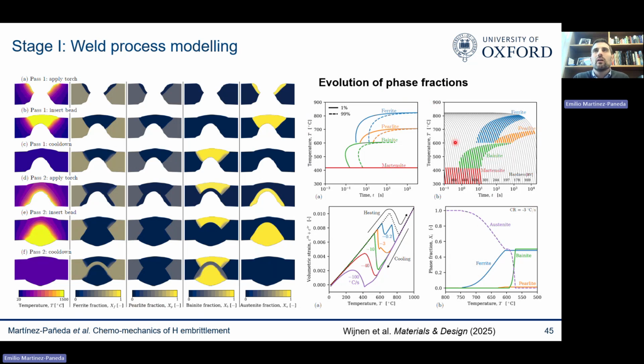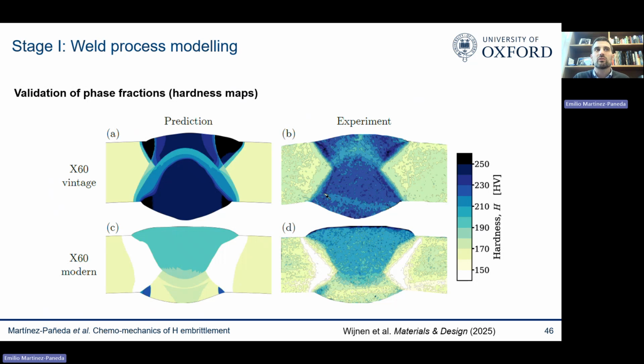These models are relatively empirical, but they're actually quite good, I was quite impressed by them. You can see that, depending on your phase fraction, what is the hardness of your material, so that allows you to validate. You see here two types of welds, we apply the same welding protocol, and as you can see, we got actually quite a good agreement when it comes to the hardness maps, experiment versus the model. So I was quite impressed with these models.